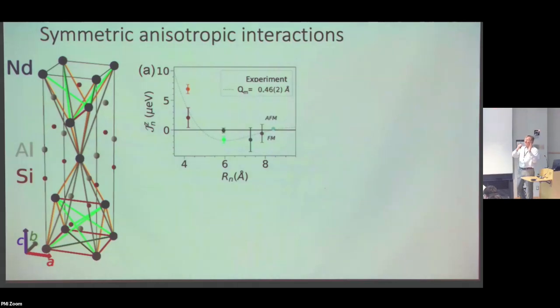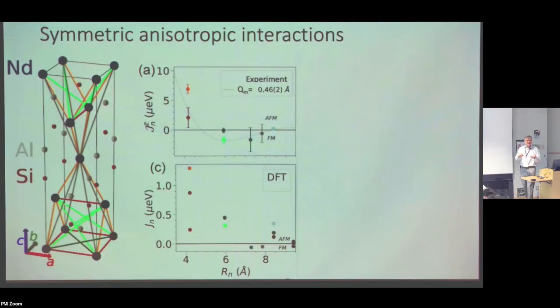The high quality data, the analysis of the full pixelated data set, and you can really get these exchange constants coming out. And then we can make comparison to the paper that stimulated some of this additional work. They actually had in their paper the DFT determined exchange constants, in absolute units. And this is the comparison. So it's not so bad in a sense, but there is a difference, which is that there tends to be very clear evidence for an alternation in the sign of the exchange interaction in the experimental data, and less so in the DFT result. And we think that that's a distinction.